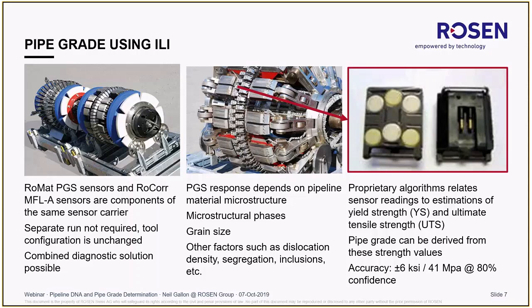The PGS response will depend on the pipeline material microstructure. That can cover a multitude of different factors. It includes the microstructural phases present, so your pearlites, your ferrites, your metastable phases, bainites, martensites, etc. It does depend on the grain size. It depends on the lath spacing or the lamellar spacing within the pearlite. It depends on multiple other factors, including dislocation density, amount of segregation, your non-metallic inclusions, etc., etc.